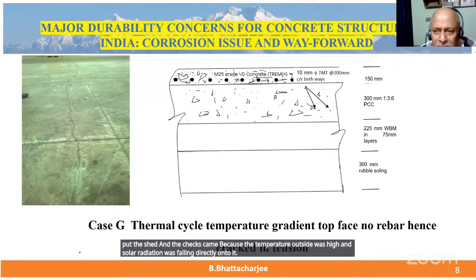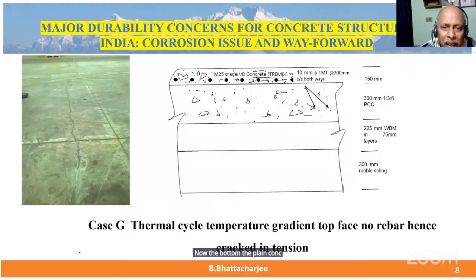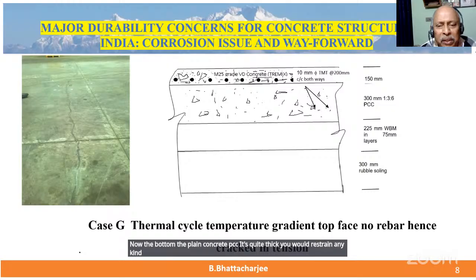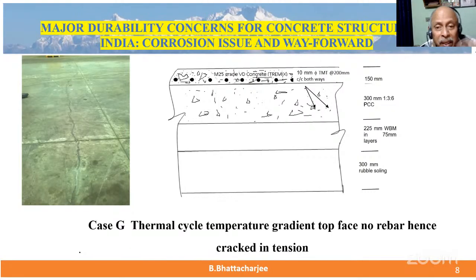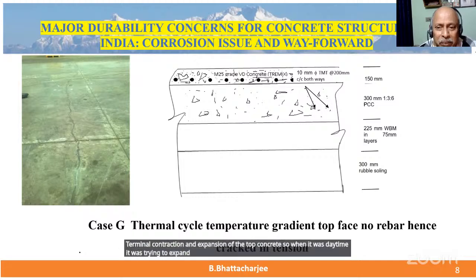Now the bottom, the plain concrete, PCC, is quite thick. It would restrain any kind of thermal contraction and expansion of the top concrete. So when it was daytime, it was trying to expand. Possibly the expansion was resisted, so compression was there in the daytime. And it would go to say 35, 40, or 37 plus another 10, 12 degrees centigrade because of solar radiation falling onto it.